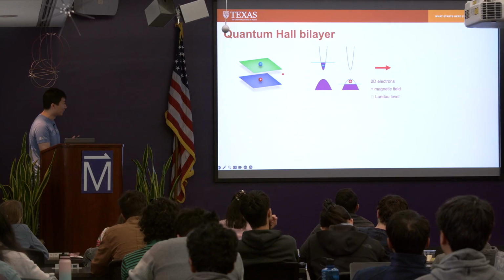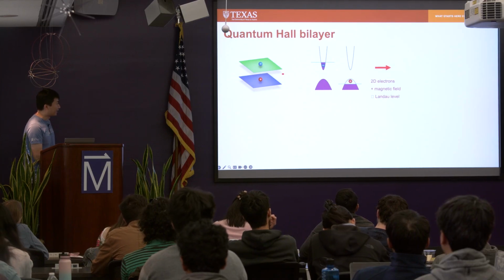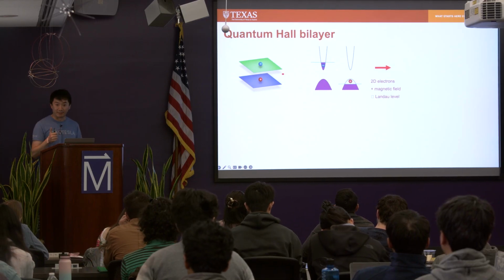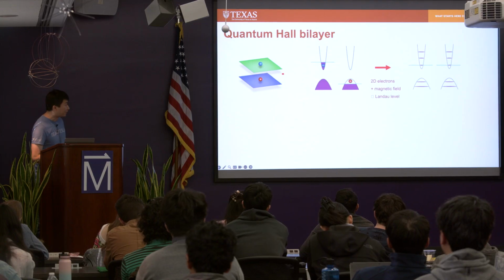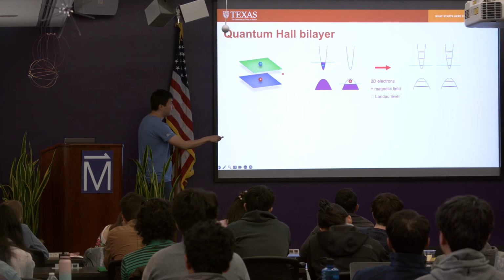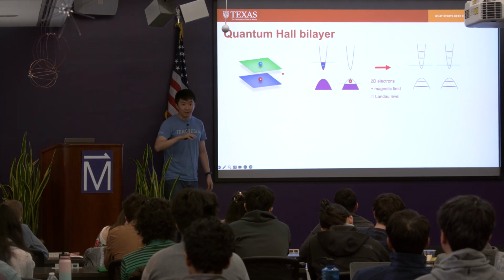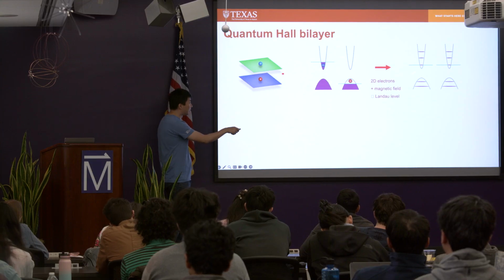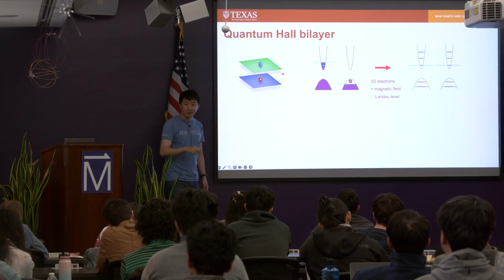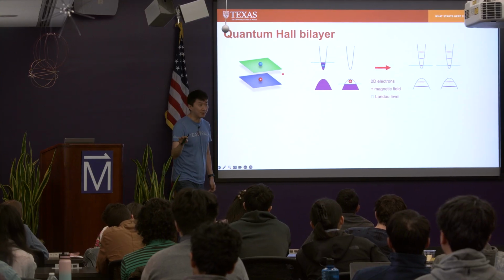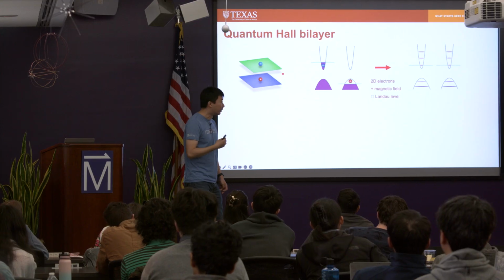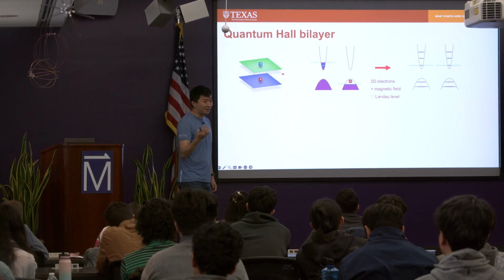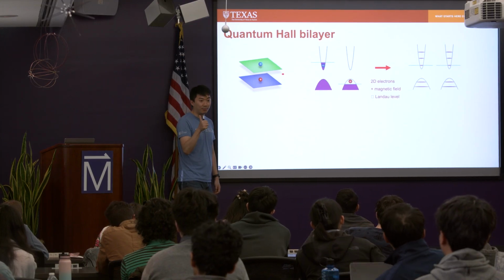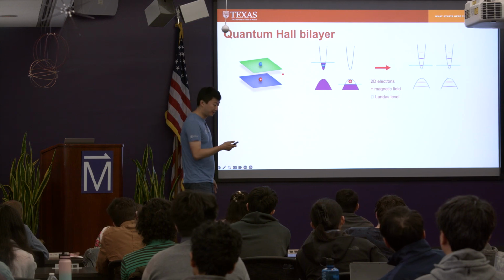There's an easier solution where you get a 2D electron gas, you just need to apply an out-of-plane magnetic field, right? Then you get these Landau levels forming across each layer. Regardless of how dispersive the original band is, once you have Landau levels, the dispersion goes away, right? So you can get an infinite amount of density of states that's determined by how big of a magnetic field you're applying, right?